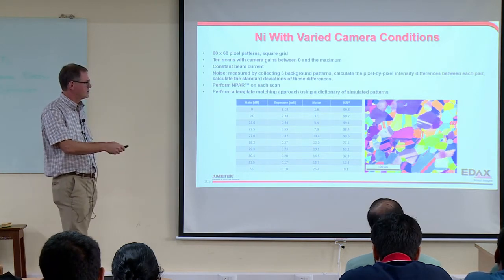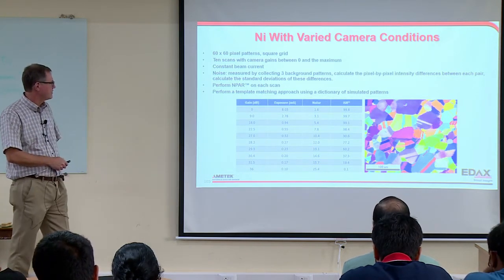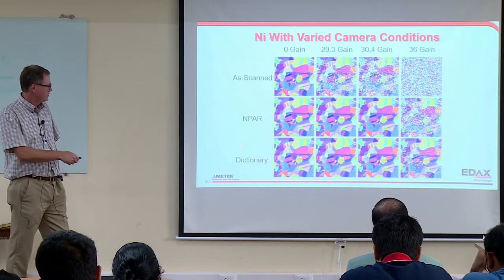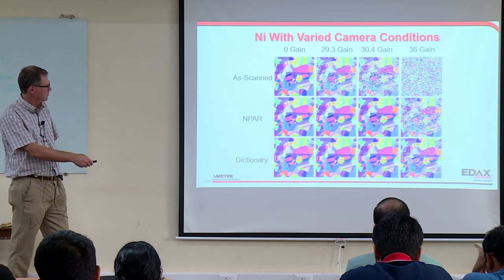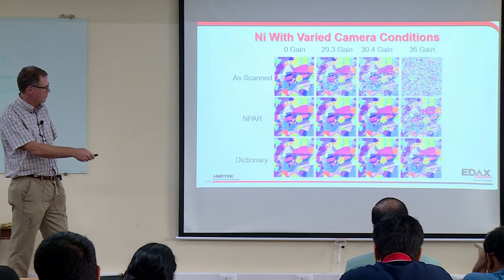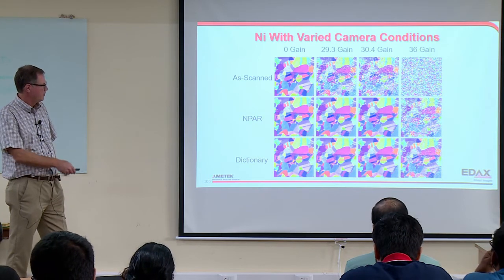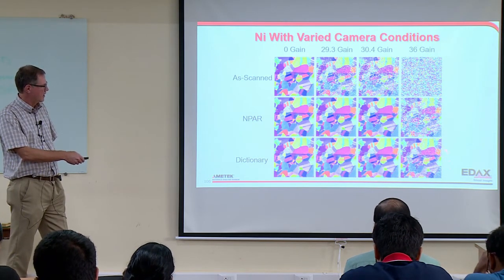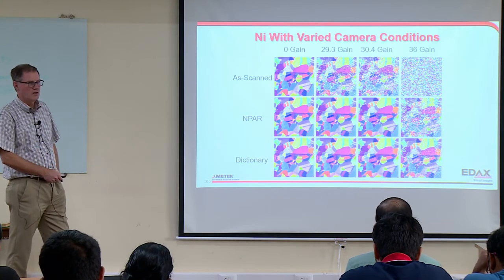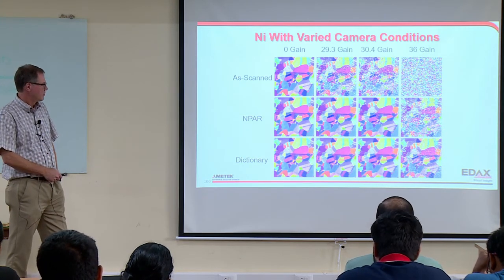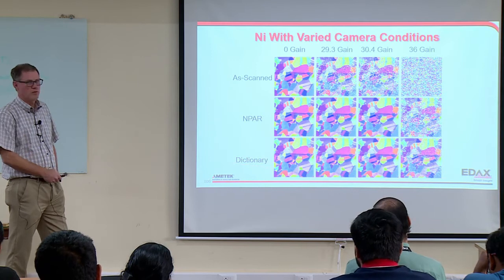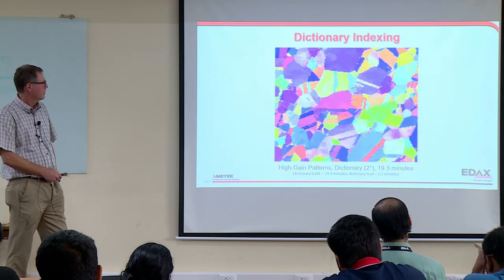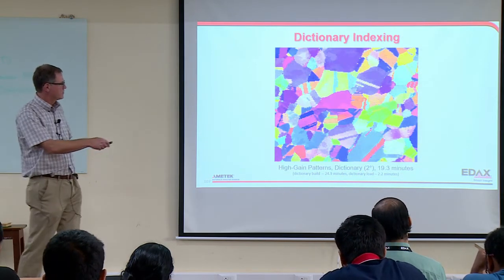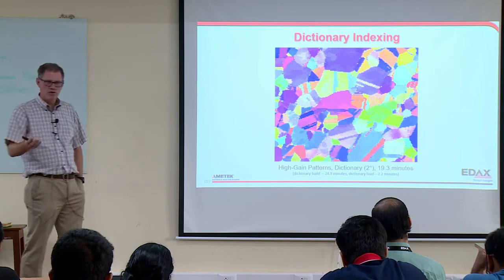So once again, this is my nickel I did with different gains, and we're going to see how it does. There's the dictionary. It does really well. Remember, NLPAR was actually even a little better. But you can see this really collects data that is a big improvement, even over NPAR. So dictionary seems to work really well when we have really poor patterns. The nice thing about it is we capture the details. There's no smearing from the NPAR.